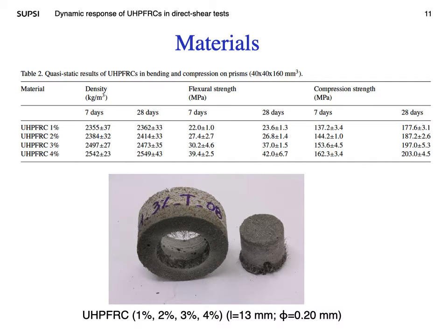Four materials are analyzed here, and they were a commercial product characterized by very high strength. High carbon steel fibers, 13 mm long and 0.2 mm diameter, were used. The addition of increasing percentage in volume of steel fiber allows achieving outstanding mechanical properties such as very high compressive strength and flexural strength. The first one are coming from 178 up to 200 megapascal, and the flexural strength from 24 up to 42 megapascal.